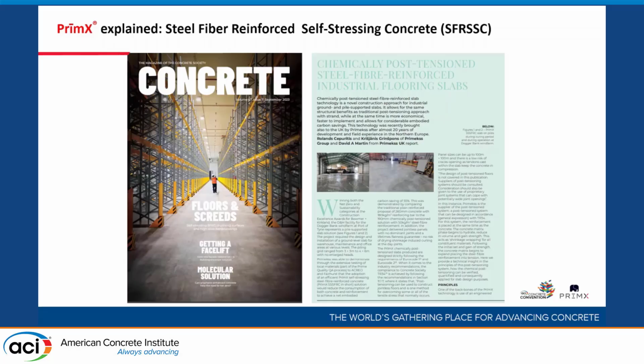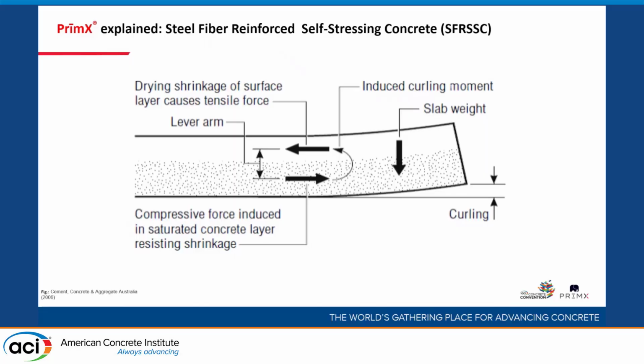So if we look at, for example, the slab on ground situation, one thing is that in many cases the section depth of slab on ground is just dictated by the fear of curling. So in many instances you make slabs very thick just because you think they're going to curl, because there will be too big a gradient of the relative humidity between top and bottom, and also there is some perception that you need some slab weight to prevent it. So when it's chemically pre-stressed, you can compensate. First of all, of course, you pre-camber it to some extent because it's typically more expanding on the top than the bottom part, but also you don't get a big shrinkage deformation gradient, and in that way you are not limited by curling problems when you choose the slab depth.